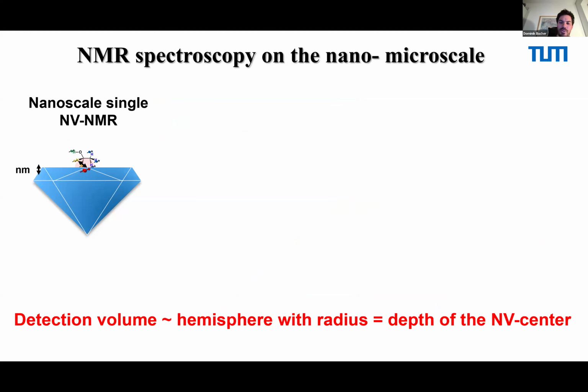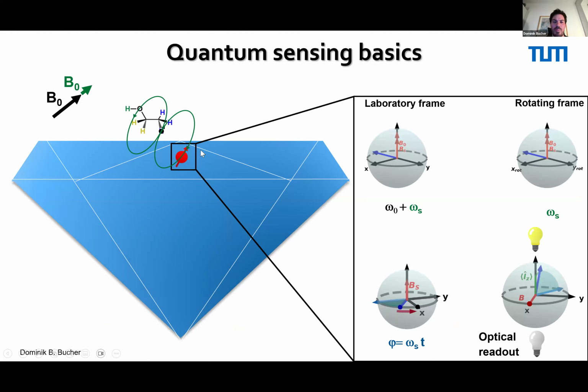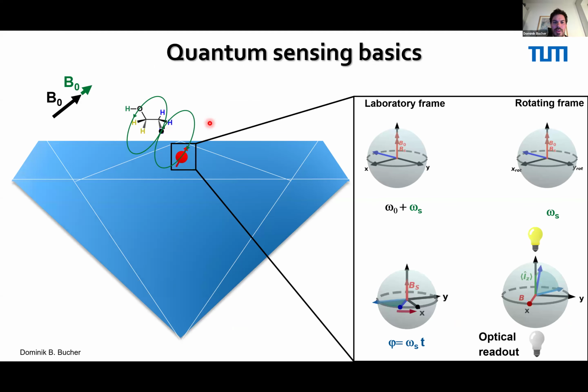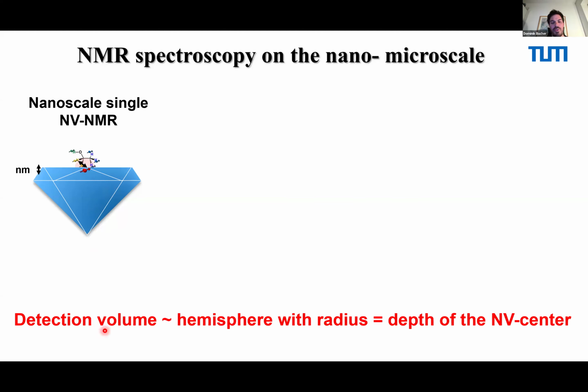Okay, so now the question, of course, is how far do we see? If we bring the NV center to the surface, we are, as I said, mainly interested in sensing something outside of the diamond. What's the detection volume? If you go back to the previous slide, you would integrate over these dipolar moments here. If there are many molecules, you integrate over these dipolar moments, and then you get this rough rule that the detection volume is a hemisphere with a radius equal to the depth of the NV center. So if the NV center is a couple of nanometers deep, then your detection radius would also be a couple of nanometers. If you bring the NV center deeper and deeper, then the detection volume gets larger, but typically the signal, depending on what you measure, in some cases goes down.